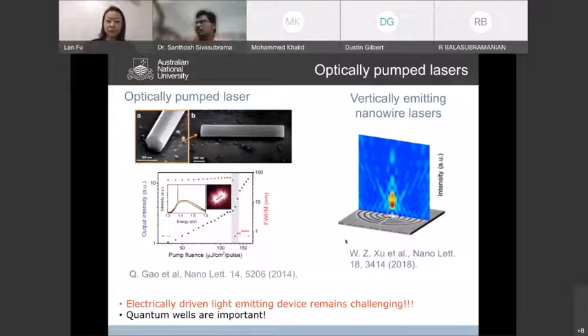However, although we have shown its good properties from optical pumping, achieving an electrically driven light emitting device from nanowires still remains very challenging, for obvious reasons. If we have just a small nanowire as the gain medium, it is sometimes not sufficient for lasing. Also, making electrical contact is always challenging in this material, because of the nanoscale and nanofabrication. Any loss introduced by the contacting and localized heating will become a very challenging issue for this kind of device.